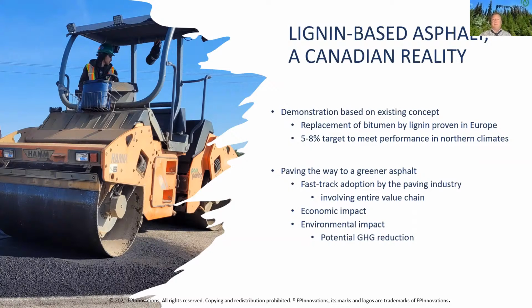The objective of this project is to make a demonstration under our much colder northern climate, our Canadian regulations, and with the kraft lignin that our industry can produce. We're not targeting a 50% rate, as we already know that lignin responds very well at high temperature, but not as well at low temperature. Our assumption was a 20% substitution, but our initial lab results show that we should now target 5 to 8% of kraft lignin as is to ensure performance gains only.